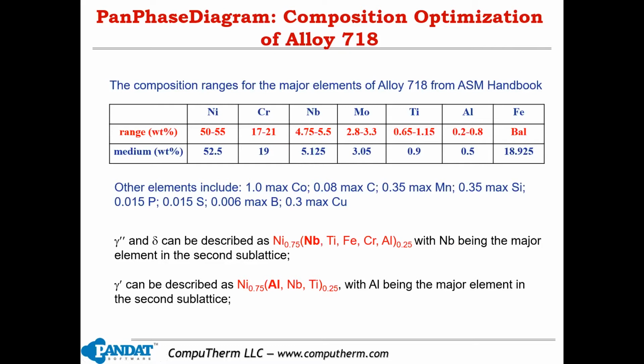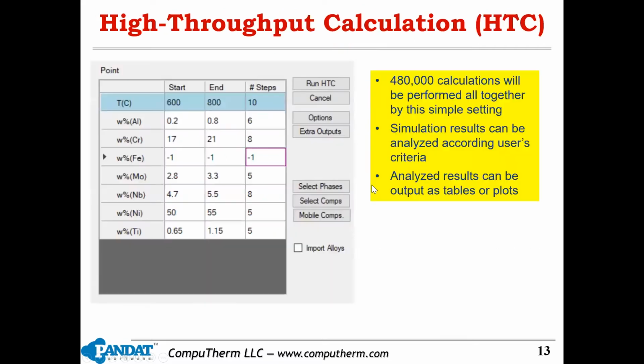So with a high throughput calculation, we can perform massive calculations in the composition space. And then we allow the composition of each element to vary in the spec range, okay? For example, here, I just show you how we can set up a high throughput calculation. In this case, aluminum can vary from 0.2 to 0.8%. And then I give 6 steps. Basically, you can vary it from 0.2, 0.3, and 0.4 all the way to 0.8, all right? And chromium from 17 to 21%, I give 8 steps. And so on and so forth for all the other elements.